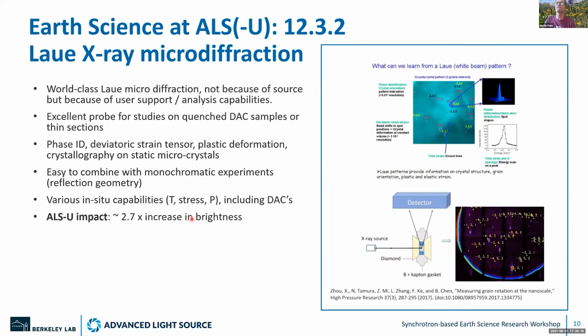In earth science applications, the most common kind of samples are petrographic thin sections, where scans with maps are produced with the kind of information I mentioned before, that is phase maps, rotation maps, strain maps, etc. That doesn't mean that the beamline cannot be interfaced with some kind of non-ambient conditions, mostly a temperature stage. They can do mechanical stresses and pressure, and there are also published examples of diamond anvil cell work combined with Laue microdiffraction on beamline 12.3.2. This was by Shaoling Xu, who was first a doctoral fellow at ALS and then a postdoctoral fellow together with Lowell Miyagi.